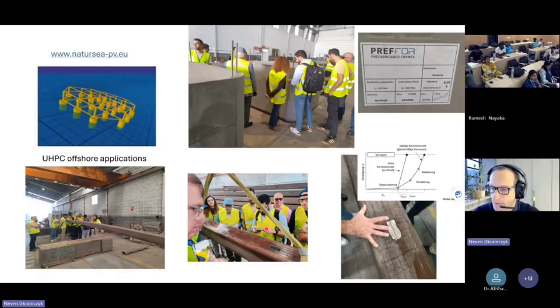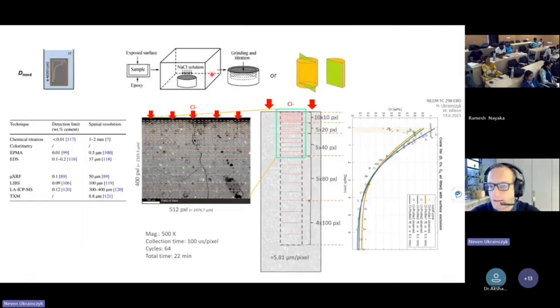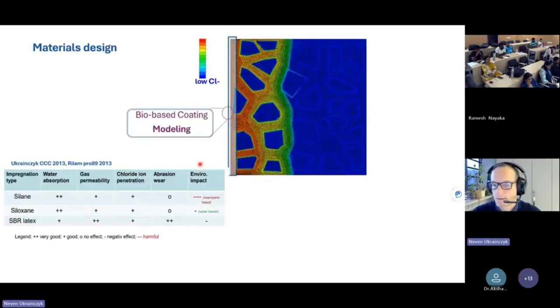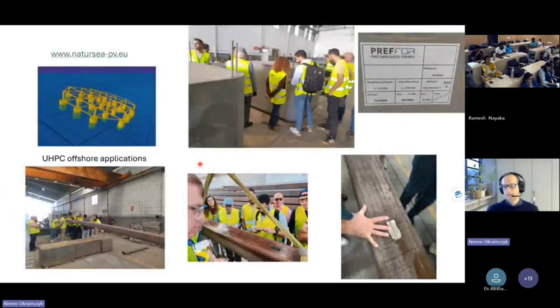So how would you measure then? What we are doing actually is exposing it to seawater in a lab test, so like here, this method. And then, of course after a few months, because it's UHPC, we only have less than 1 millimeter penetration. But then we will use this microscopy. I have the samples here and we will try to measure, at least we can get the profile in the first micrometers. Yeah, there is no other way. At least we have something.